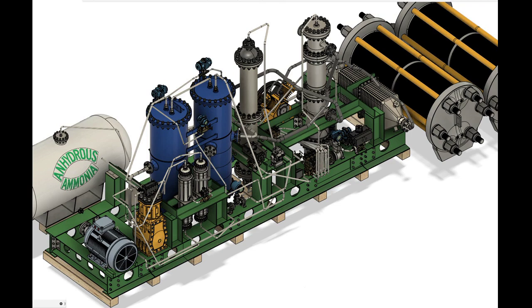In 2006, the Mosaic Faustina ammonia plant in St. James, Louisiana, experienced a catastrophic failure in the synthesis loop boiler feed water heater, causing the separation of the inlet channel from the heat exchanger housing. Upon forensic examination, the failure was traced to hydrogen-induced cracking.